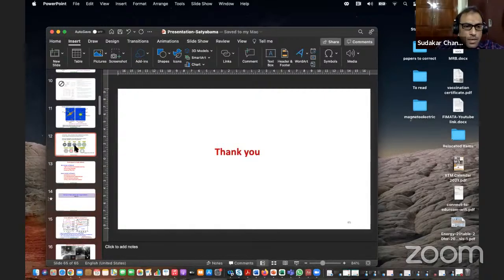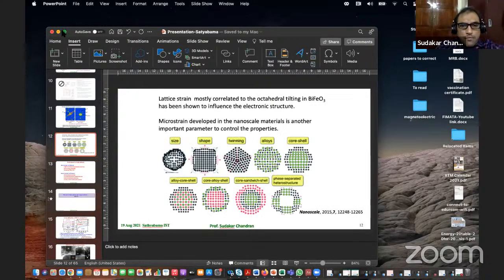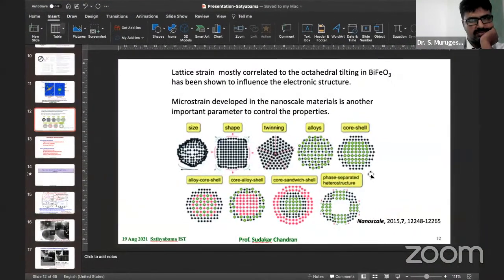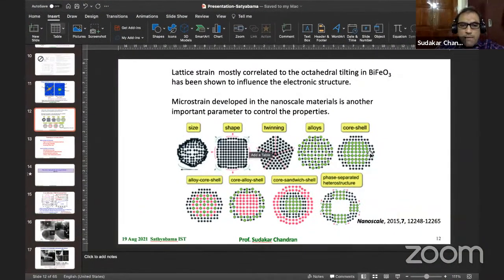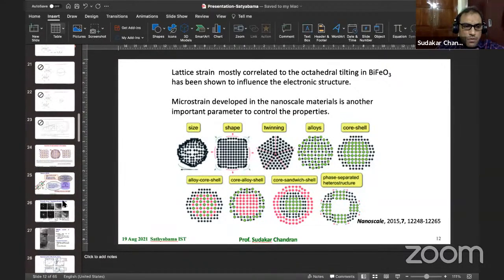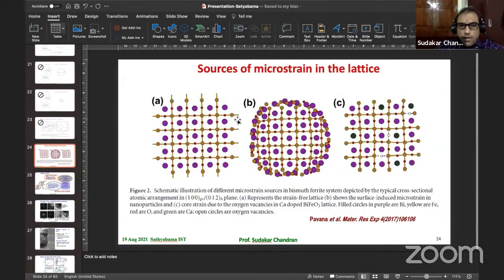So the lattice strain, as I showed here, can be controlled by various methods. In our case, we did it by oxygen vacancy, as I showed in one of the examples. A perfect, large, infinite crystal will not have any oxygen vacancies, therefore it's all perfect. But if you reduce the size, oxygen vacancies from the surface come into the picture, and therefore there is a lot of push and pull because of the termination of the bonds and undersaturated bonds,